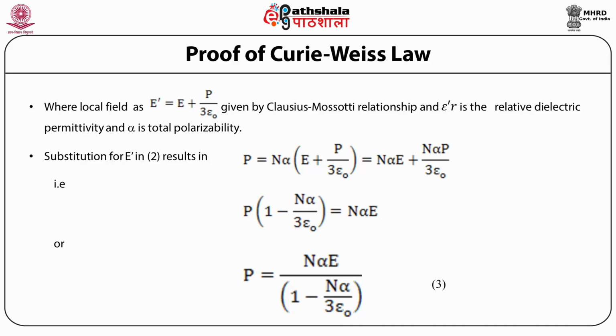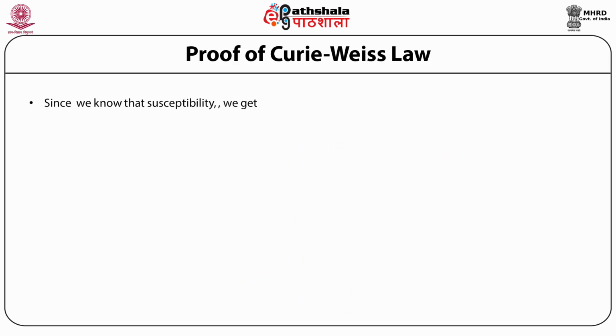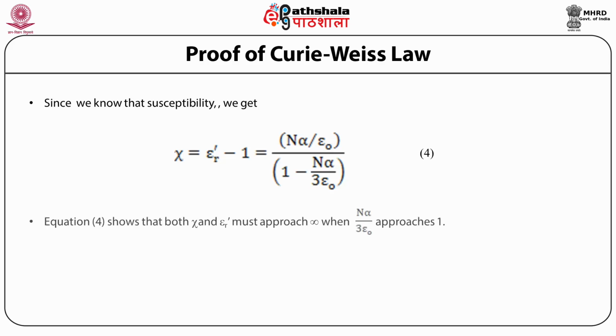upon 3 epsilon naught. Since we know that the susceptibility is given as epsilon r dash minus 1, it is equal to P upon epsilon naught E. So we get the value of susceptibility as n alpha by epsilon naught divided by 1 minus n alpha upon 3 epsilon naught. This equation shows that both susceptibility and relative permittivity must approach infinity when n alpha upon 3 epsilon naught approaches 1.